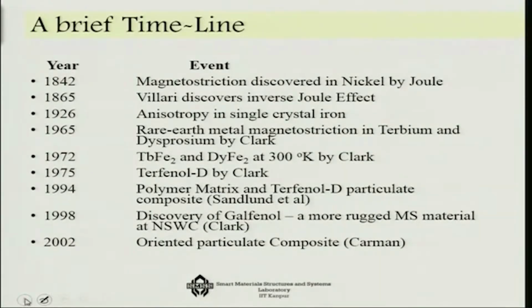Now, we talk about a brief timeline of the magnetostrictive materials. As I told you, James Prescott Joule first discovered magnetostriction in nickel, and that was Joule's discovery, in 1842. In 1865, the reverse effect came to the notice of Villari. So, he found out the inverse of the Joule effect. In 1926, people were able to see this anisotropy in single crystal iron due to the development of material science. And in 1965, for the first time, beyond the general ferromagnetic materials, people found magnetostriction in rare earth metals like terbium and dysprosium. This was initially found out by Clark and then other people in the Naval Ordnance Laboratory.